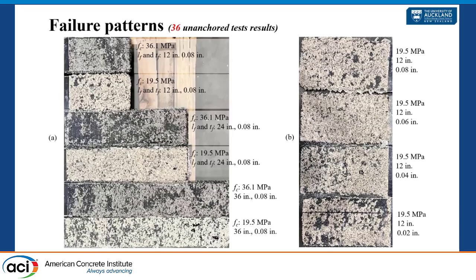Then we move to the failure patterns. All the tests failed by debonding, so we can compare all three different parameters under the same condition. On the left, we compared two parameters: one is concrete compressive strength, another is bonding length. We didn't see a really clear change for the bonding length, but we saw a clear change for the concrete compressive strength.